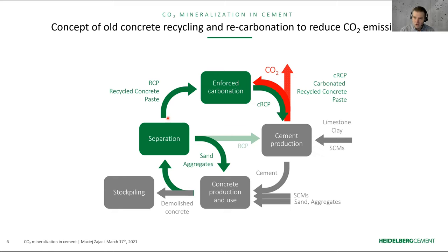However, I would like to point out the advantage of the process of carbonation of the recycled concrete paste, because we are gaining in terms of CO2 in two places. Of course, we are sequestering a lot of CO2, and as I said, theoretically all the CO2 released from the limestone during the clinker production. The second advantage, which is very important, is that we are able to use the carbonated material as a replacement in composite cement production, and as I showed in the example, for higher replacement ratios in the range of 40% or more. So we are gaining within this process in terms of CO2 twice, and this is a very important advantage in our eyes. But we are, of course, considering several solutions, and we are not saying that this is the only one.